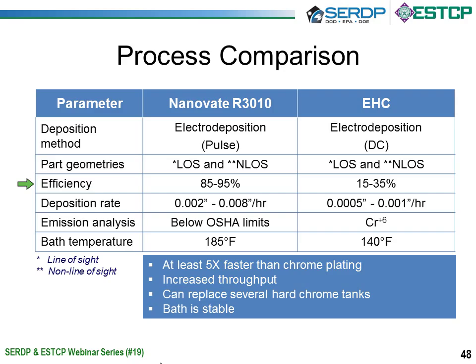In addition, chrome plating is one of our top candidates for removal. We just finished an assessment that we performed for ESTCP, chrome plating processing infrastructure at our fleet readiness centers across the nation. It accounts for about 30% of our total usage of hexavalent chromium, and it results in roughly around 25,000 gallons of just infrastructure. Those are plating tanks and rinse tanks across our facilities. So this is our top project that we are trying to implement across site for minimization of hex chrome exposure.